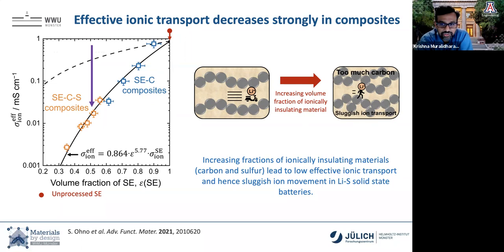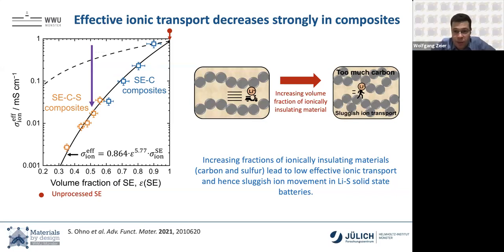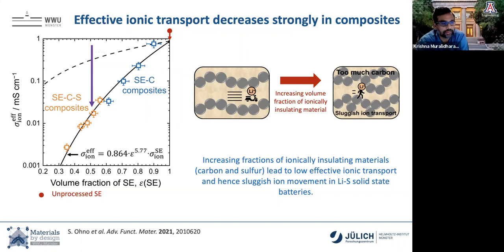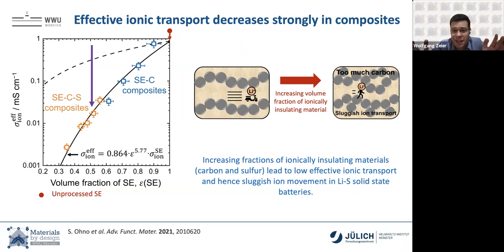Yeah. I had to step away for a couple of minutes, but I assume that you didn't show too much NMR work. Have you considered carrying out orthogonal NMR work to look at lithium residence times and diffusion and correlate to the effect of disorder? Yeah, we do that, usually in collaboration. I didn't show any of that work here, but it does correlate. Oh, it does correlate. Okay. It does correlate, yeah. Cool. It's really the case that impedance, NMR, and theory actually tell the same story.